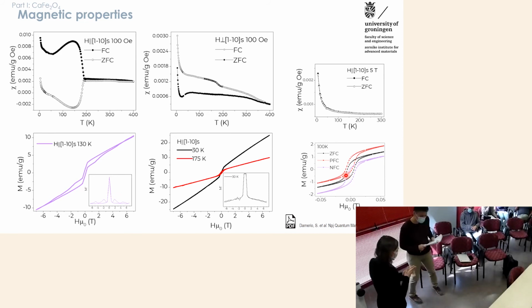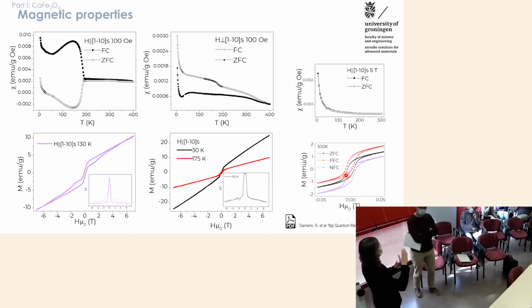Yes, what we think is that there are indeed these two different orderings. There is a long range antiferromagnetic ordering, and then these spins at the antiphase boundaries. When we apply a certain field, which can be positive, the spins at the antiphase boundaries orient with the field and preferentially stay oriented like this. So when you field cool, you will have this extra net magnetic moment due to the spins, and this would induce a vertical shift in the positive direction. While if you field cool with a negative applied field, the antiphase boundary will be preferentially oriented negative.